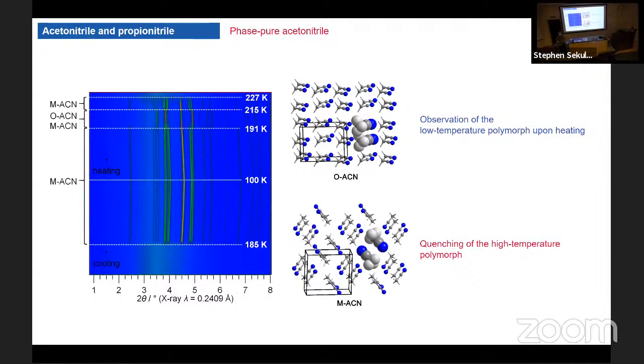How is this relatable and why is this important for Titan? Well, on one side, we can say that if acetonitrile cools down and rains down quite fast, we can have this quenching. Then the next question would be, will the high temperature form stay high temperature, or monoclinic, throughout time? There are two arguments there. On one side, it's quite cold, so it's very difficult to have a phase transformation if you don't have that energy input. Think about glass. Glass should not exist because it's a metastable form. It should crystallize. Yet glass doesn't crystallize. We all use glass. A similar thing can happen with acetonitrile.